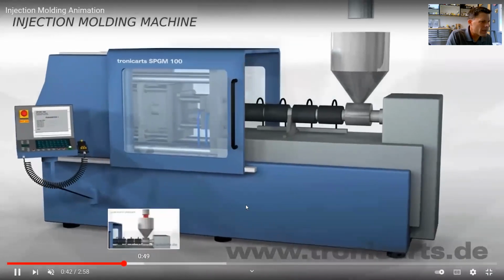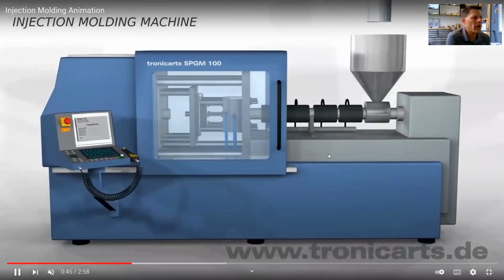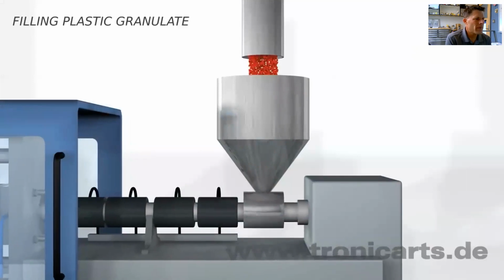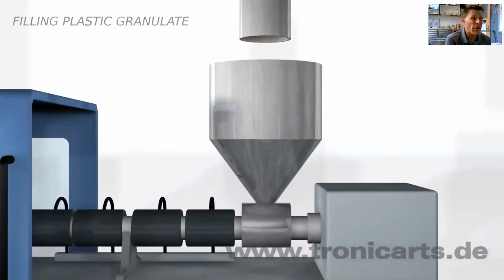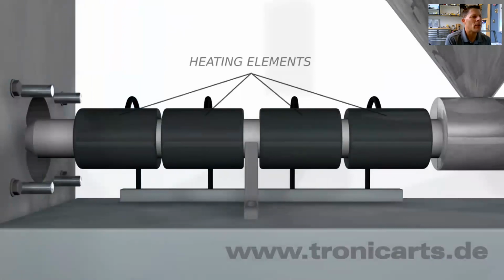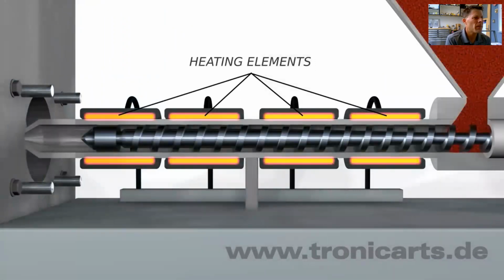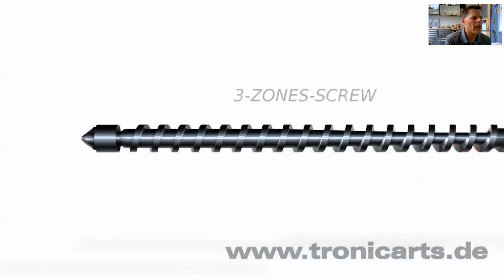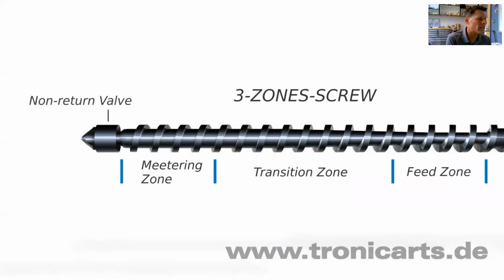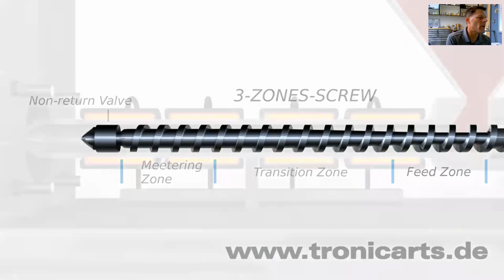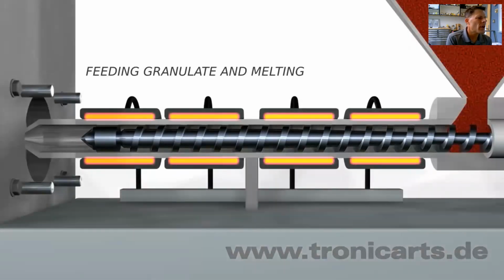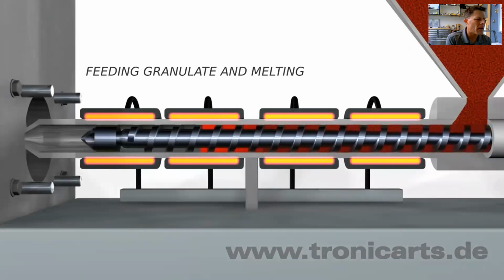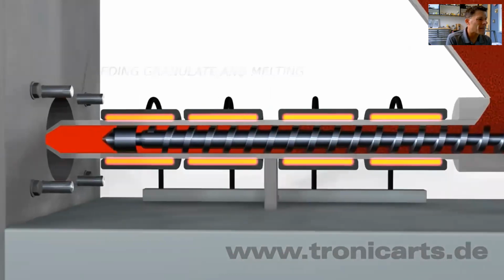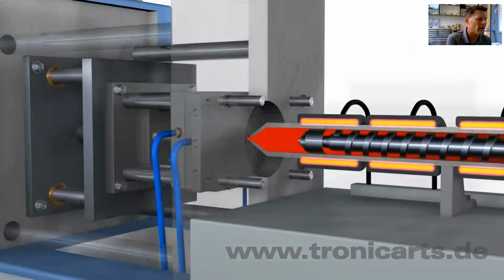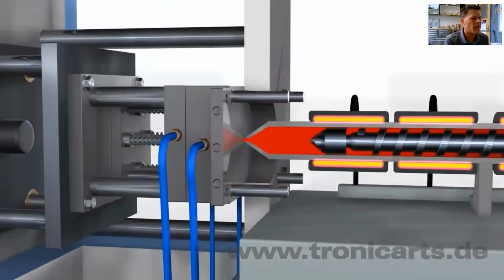So the way it works is you get your beads. They go on the top of the hopper, right? So we kind of know how this works. We put our beads in there. We put any colorant in there that we need. The hopper is going to dry out and get rid of all of the moisture that could be in that material. Once it's dried, it goes into the screw or auger. There are 3 zones in the screw: the feed zone where you first drop it in from the hopper, the transition, and the metering zone. After the metering zone, it goes into the non-return check valve. The granules start to melt and melt and melt. They're not fully melted until they get up to the metering zone right above the check valve. So on the left-hand side of that check valve is where it's melted.